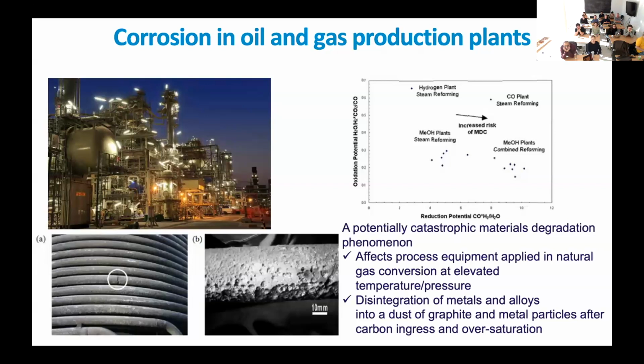So if you see here, for example, syngas itself is composed of carbon monoxide, hydrogen, water, and carbon dioxide. In this case there are risks of metal dusting that I will explain to you, okay? We are in the regime where the reduction potential and oxidation potential of these species are competing with each other. This applies to carbon monoxide steam reforming, hydrogen plants, methane reforming, and so on and so forth.